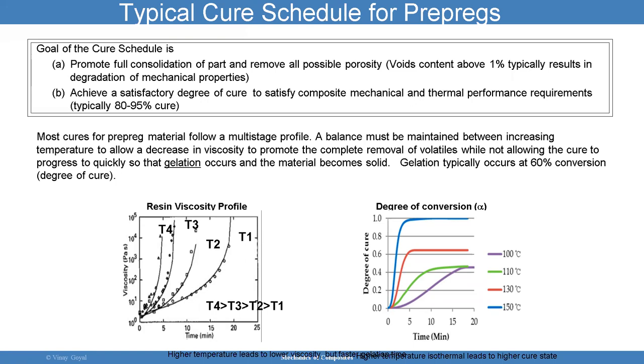Gelation typically occurs at about 60% degree of cure. So on the y-axis, you see viscosity, and time on the x-axis. And you can see here the resin viscosity profile. And you can see that at a particular time, for example 5 minutes, at 5 minutes I have a temperature T3, and that viscosity is lower than when I look at 5 minutes for T4, right? For a higher temperature cure, you can see there that I have a much higher viscosity for lower temperature, for higher temperature, I meant. So higher temperature leads to lower viscosity, but faster gelation. Higher temperature leads to a higher cure state.